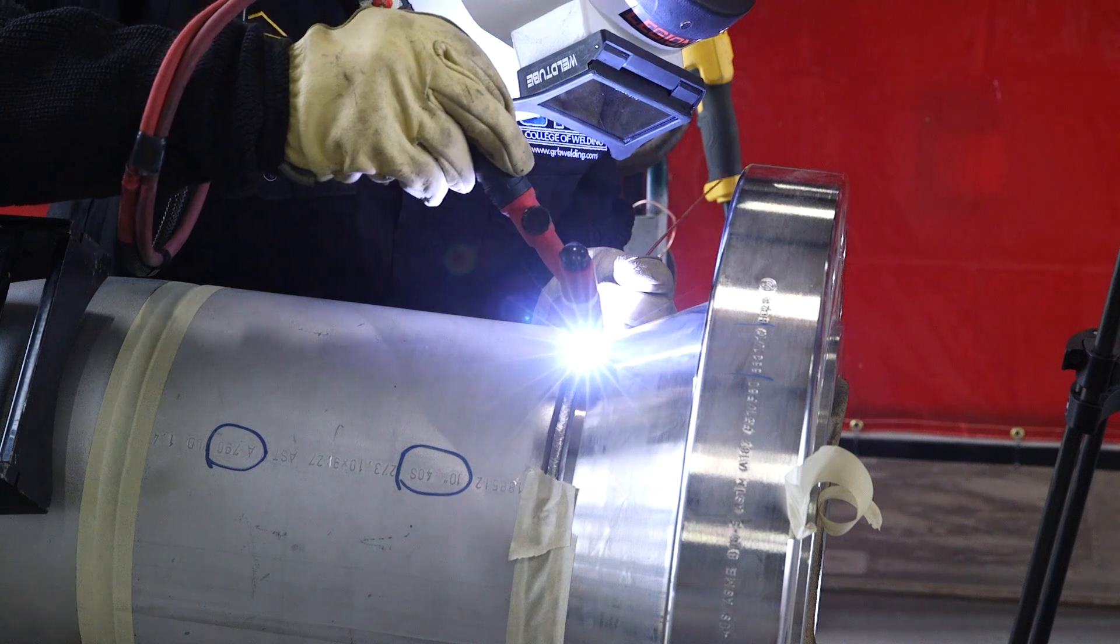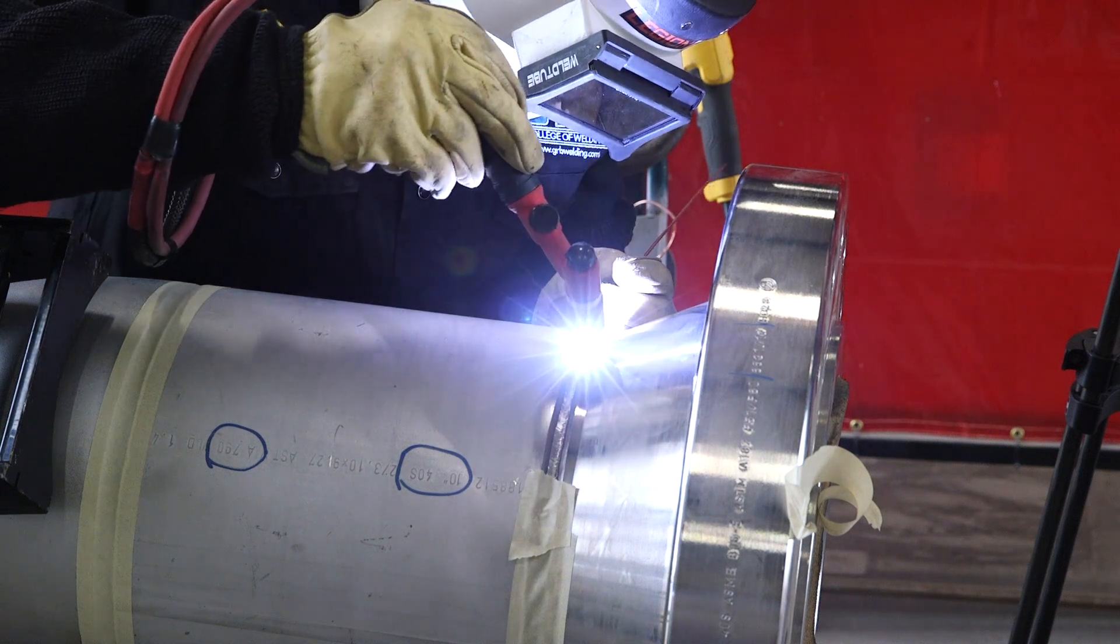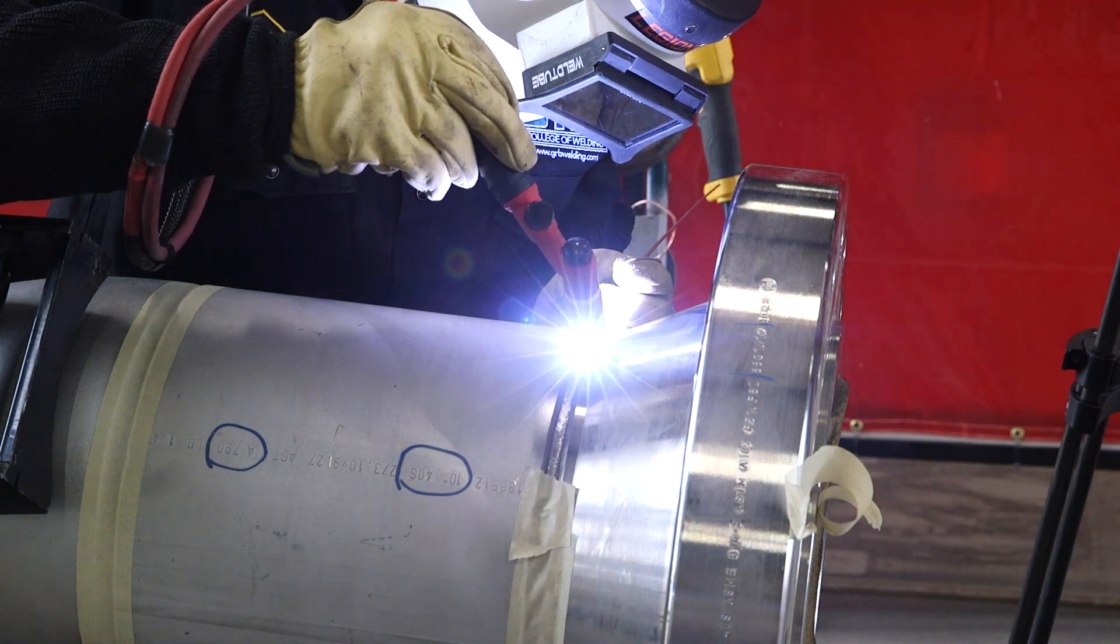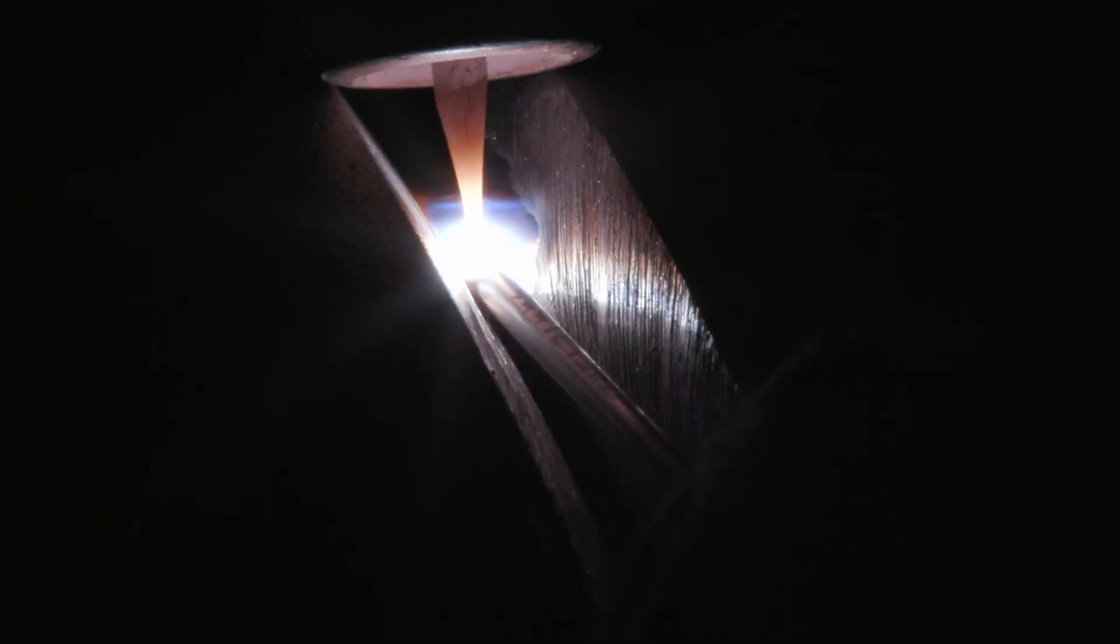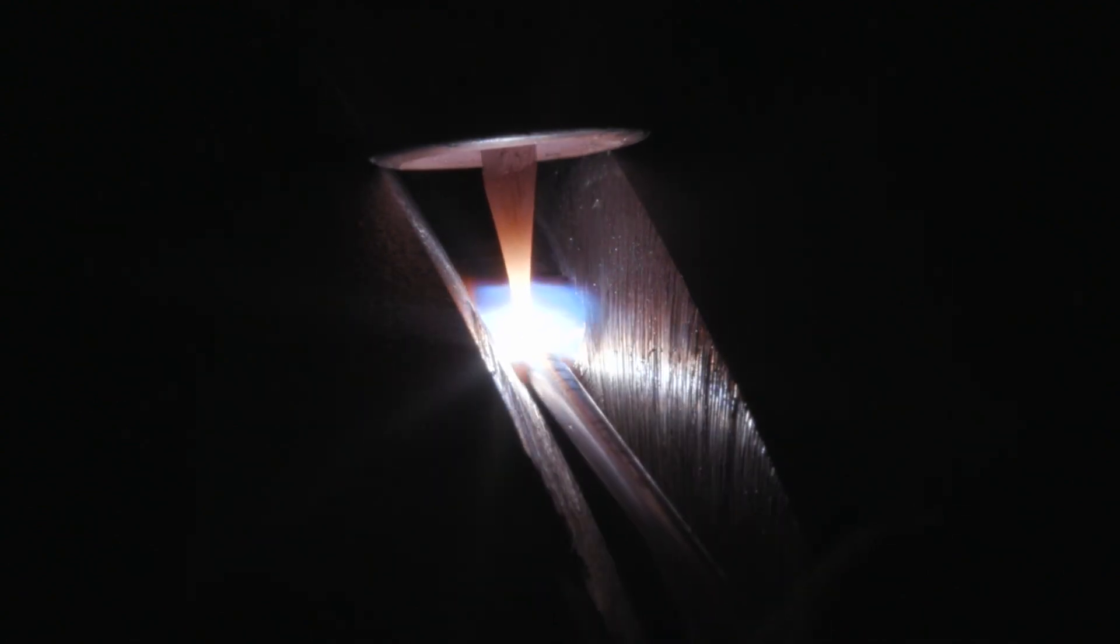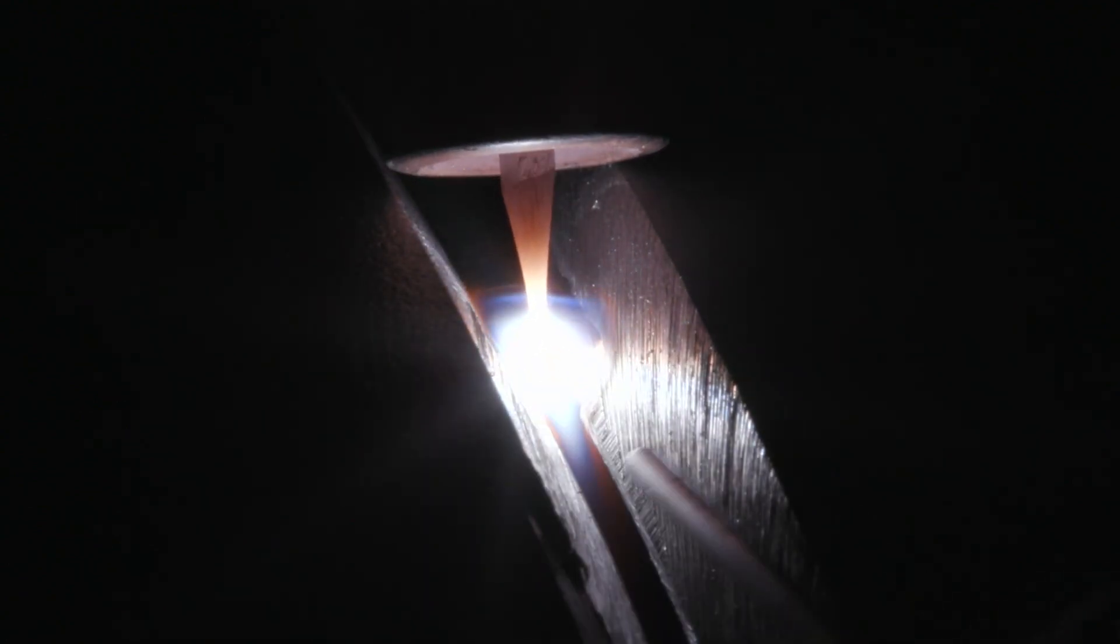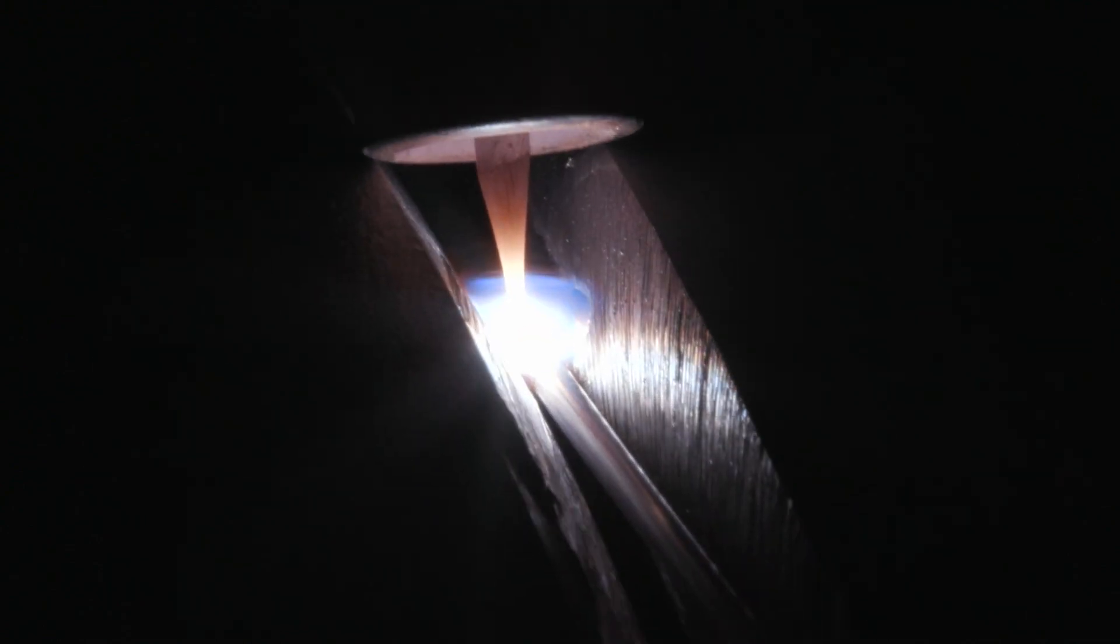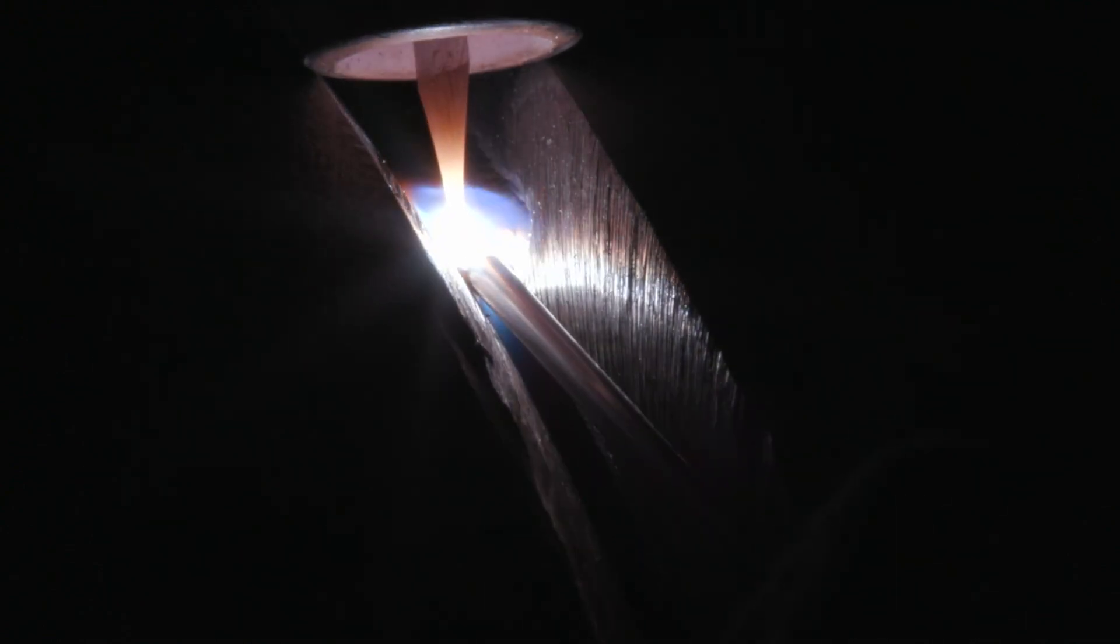Basically I'm just coming off the tack here and when you look at a lot of duplex welds, you'll see on restarts there's always a blue tinge there. The way around that is to brush that area and remove any oxides when you come down the ramp so that those oxides cannot be picked up and brought into the weld there.